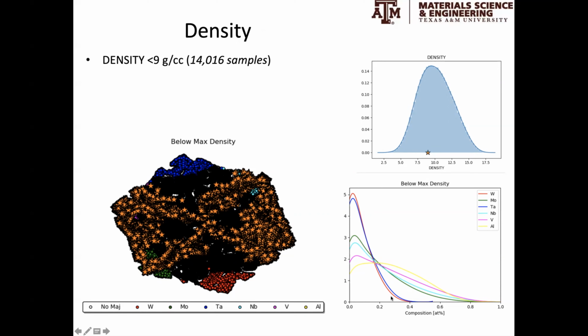And this is the signature of the chemistry: alloys that are less dense tend to have less tungsten. Alloys that have less density tend to have more aluminum than an average alloy.